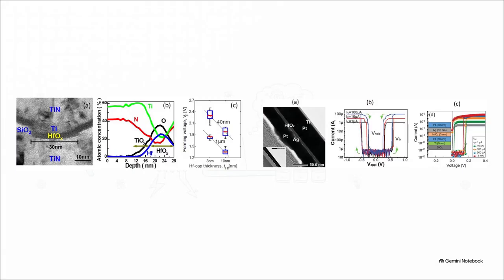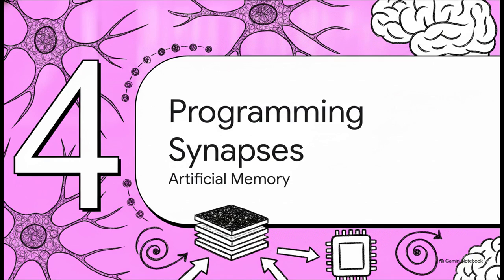I know, if we look at this under an electron microscope, it honestly looks like an incredibly tiny, incredibly complicated layer cake. But this dense material science is highly intentional. Engineers use what they call scavenging metal layers, like titanium or hafnium, sandwiched between the main hafnium oxide layer and the titanium nitride electrodes. This scavenging layer actually oxidizes by pulling oxygen from the hafnium oxide, creating an asymmetrical oxygen vacancy profile. That little chemical trick dramatically lowers the voltage needed to form the filament in the first place, saving us even more power.